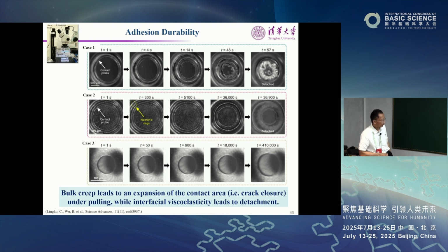Okay, so we have done a systematic study of this. It turns out that adhesion is a competition between bulk creep, deformation in the bulk of the material, and interface viscoelasticity. If the bulk creep dominates, as in case 3, the contact area under tensile force actually increases. It doesn't decrease. So when I pull two objects apart, you would think the contact will shrink, right? But if the bulk creep dominates, the interface actually grows in contact area. This is very counterintuitive. The reason is that the system wants to minimize energy, to minimize surface. By having the contact area grow, the surface energy is reduced.